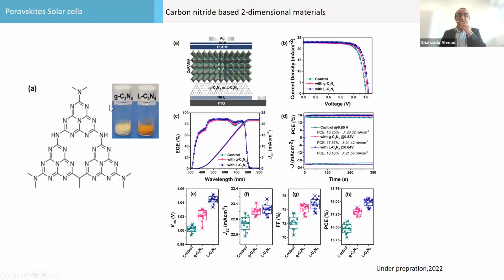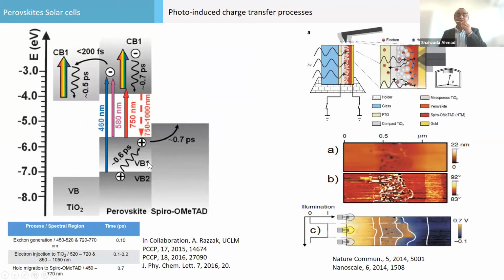So we got two different types of 2D materials from them. It's carbon nitride from solvothermal and solid state synthesis, and we made devices out of it, and the devices give higher performance. Naveen has new results with close to 20%, and the stability has also increased, as he reported. Not only this, we studied with solid state NMR and other techniques, and we found they are also very good in coordinating: the amine group, NH2 group, is coordinating with the uncoordinated lead, and this is why higher stability can be achieved.